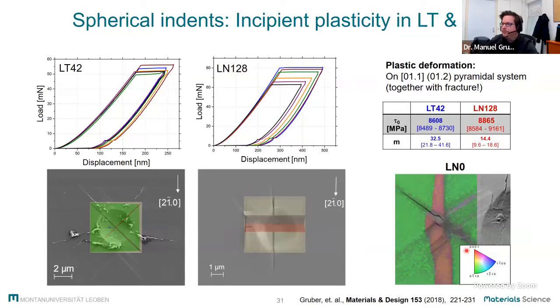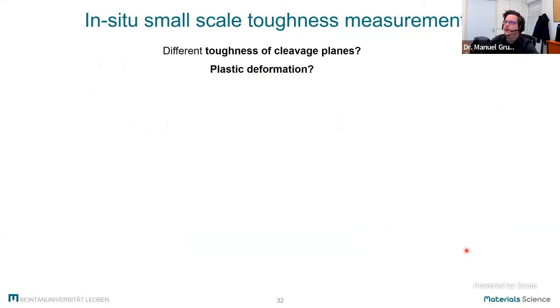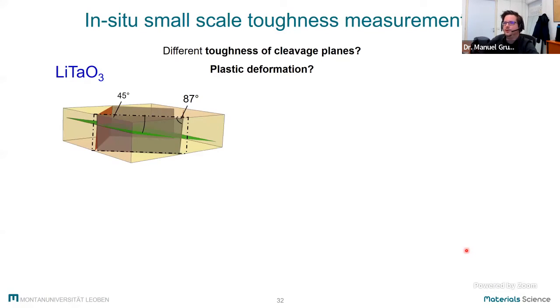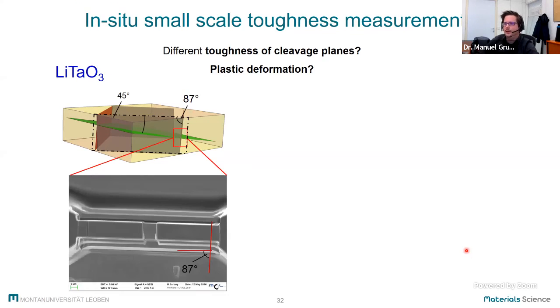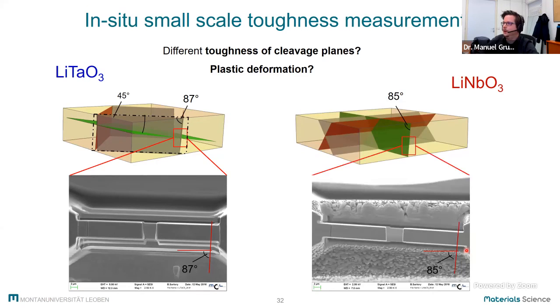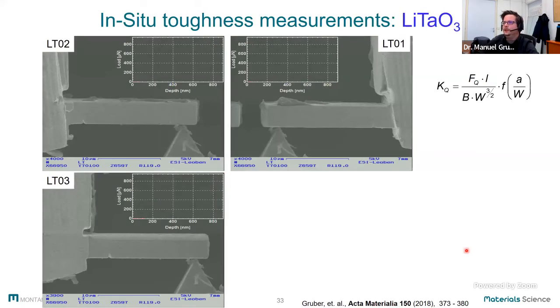Okay, so now we know that plastic deformation can be an issue in this kind of materials. And so we moved on to small scale experiments and started doing some toughness measurements in the region where this multi-layer surface acoustic wave device is made. We manufactured cantilevers with notches parallel to cleavage planes and did some in-situ testing in the SEM. So we loaded our cantilevers, you see the notch with an indenter wedge.